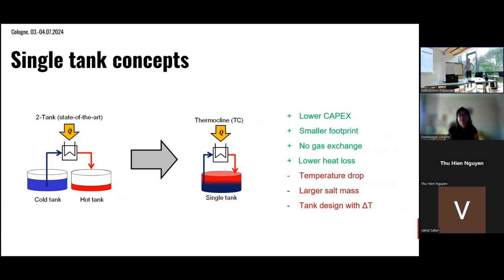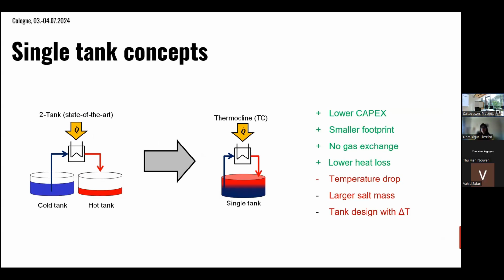less land consumption and so on. But you have a more complex system. The two-tank system has a very constant power output or output temperature. In this case, you have to deal with declining or increasing exit temperatures. And there's a slightly larger salt mass. It also depends on how much you have left in the sump. Here you have only one sump, here you have two. Another aspect is that you're not having a constant tank temperature. You're also dealing with temperature gradients inside the tank walls, which is also a topic which needs to be addressed.